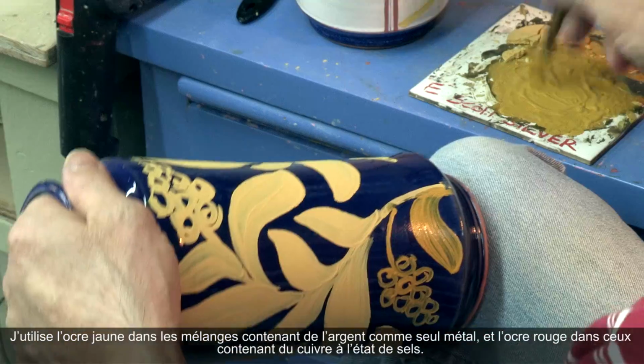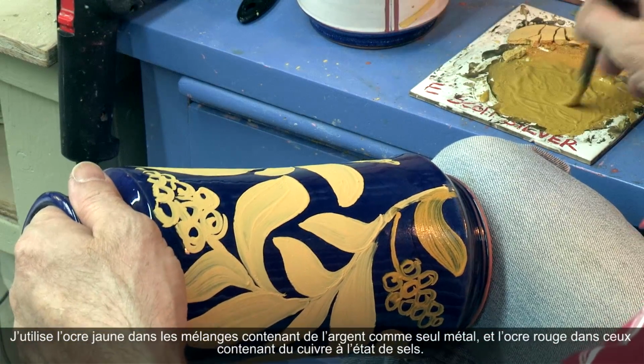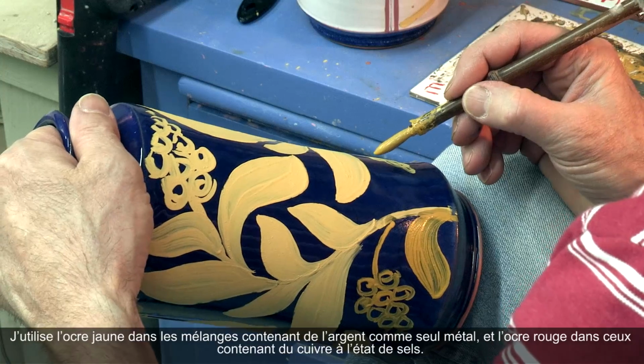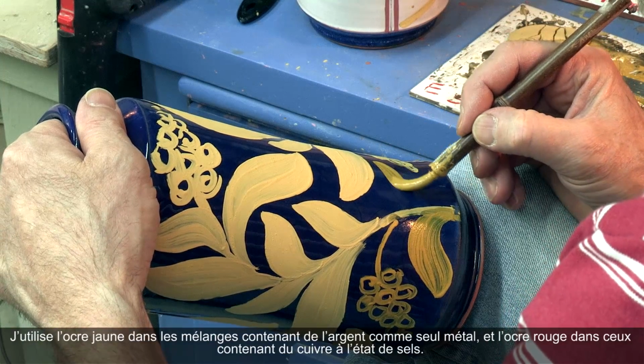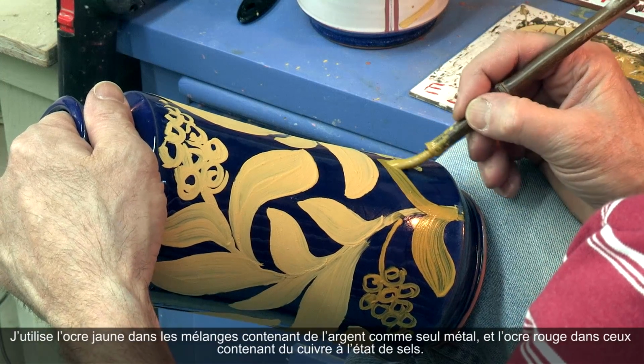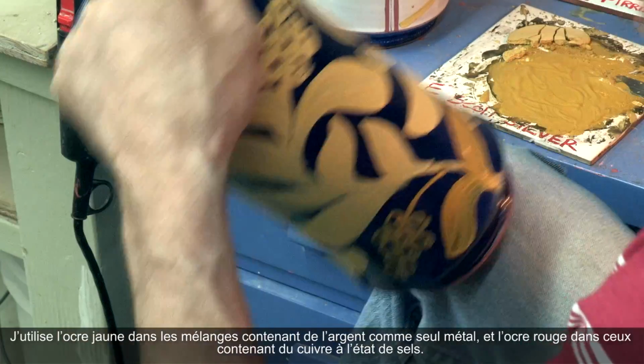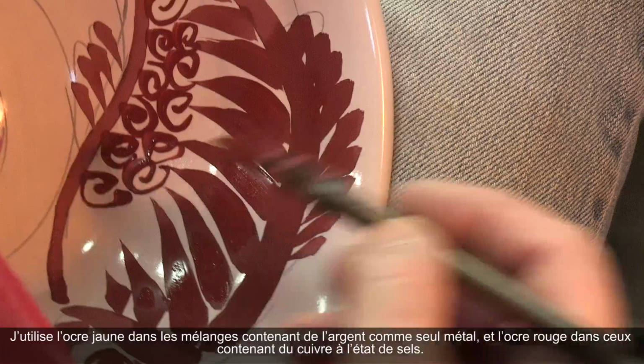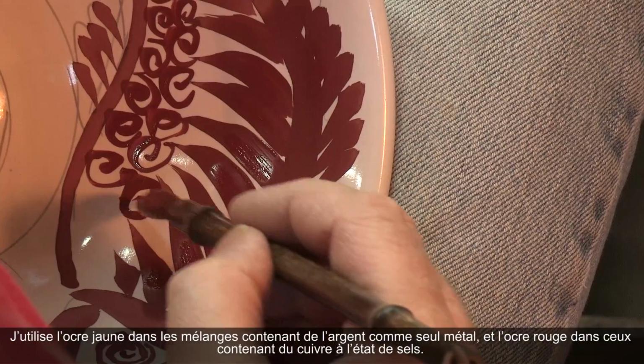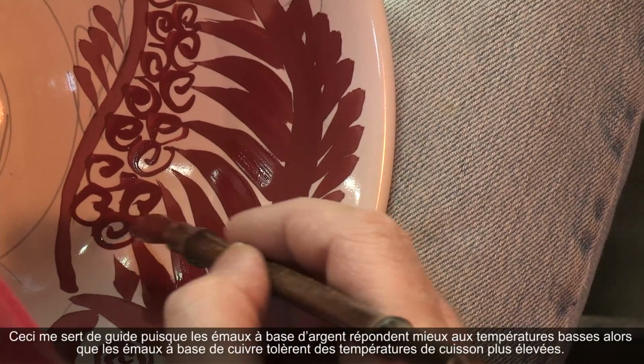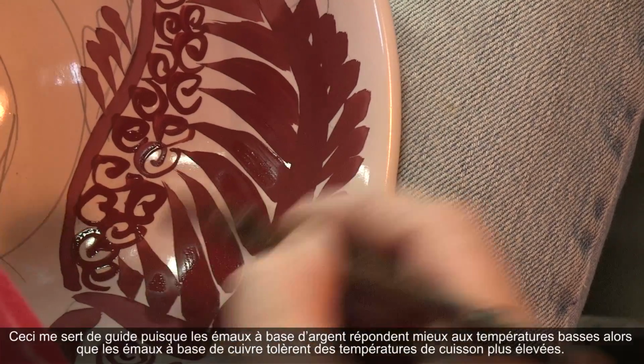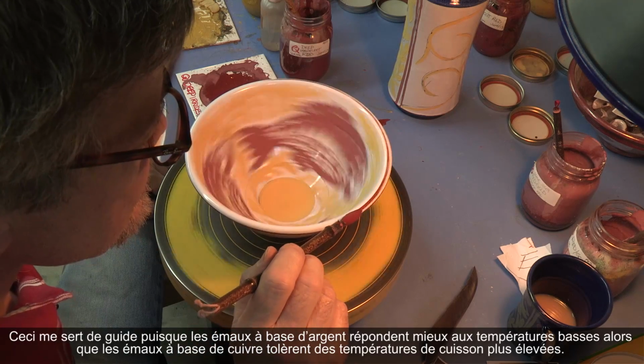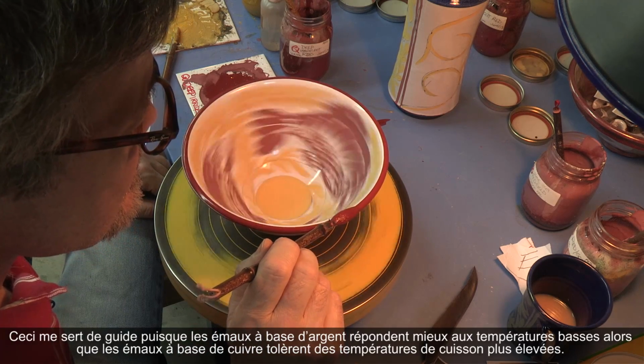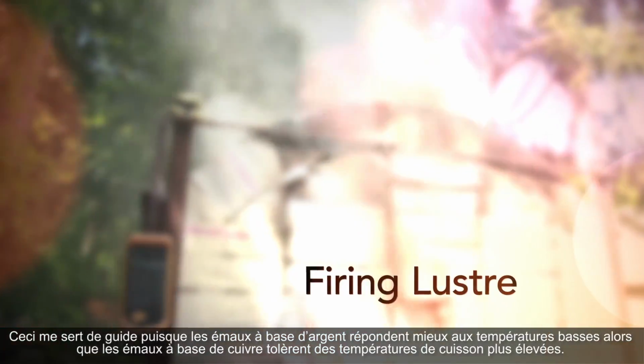So the compounds that I make that are with just silver as the metal, I use a yellow ochre, and the compounds I've made that contain copper in their salt forms, I've used red ochre in the mixture so that I have an indication, because the silvers will respond better to cooler temperatures, and the coppers will tolerate higher temperatures in the kiln.